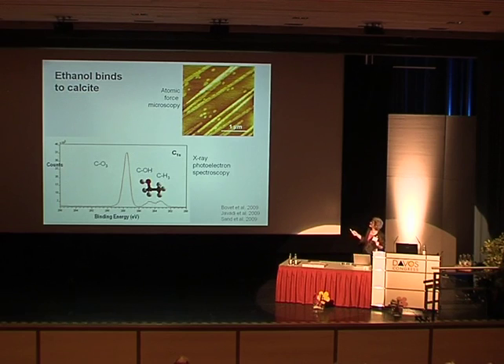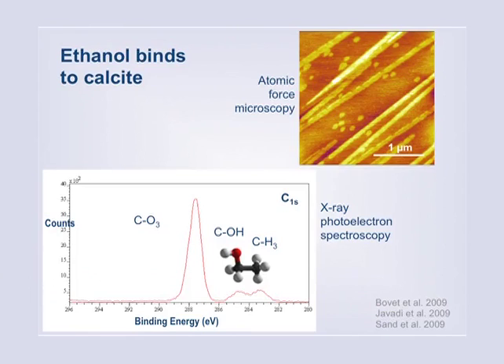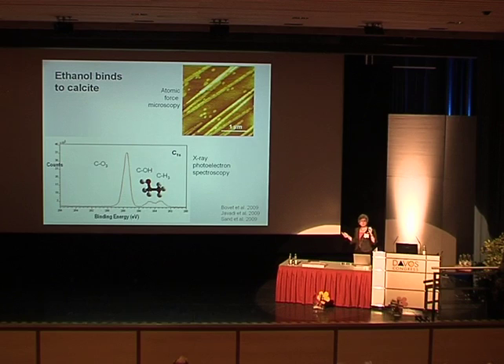Well, here we have a sample of calcite, pure Iceland spar, cleaved, looked at it with AFM. And this behavior, this attachment of recrystallized material on the surface, this is very strange for calcite. If it's only exposed to water, it doesn't do that. If it's exposed to ethanol, the OH of ethanol, ethanol is a nice one. Oh, it's gone. I had an ethanol.